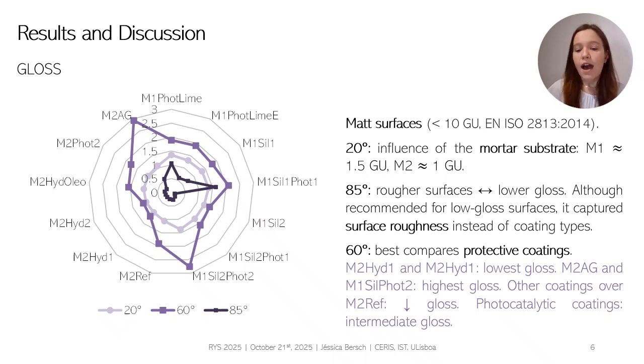85 degrees pointed to the influence of roughness. Roughness results will be presented later, but what we identified was that rougher surfaces connected with lower gloss. Although 85 degrees is the geometry recommended for low gloss surfaces, in this case, as I mentioned, it captures surface roughness instead of coating types. 60 degrees was the best geometry to actually compare the protective coatings.